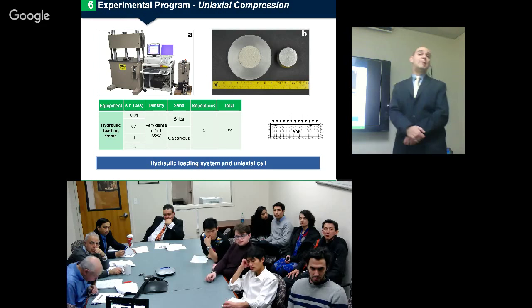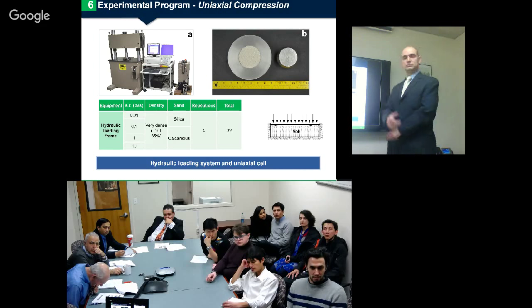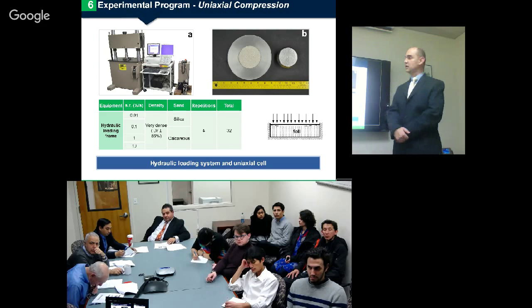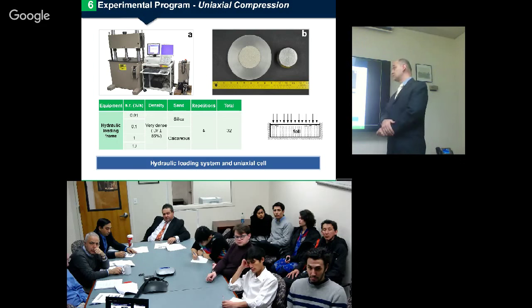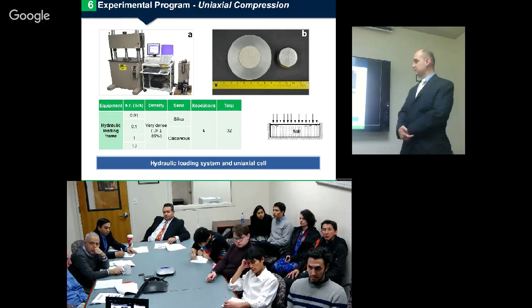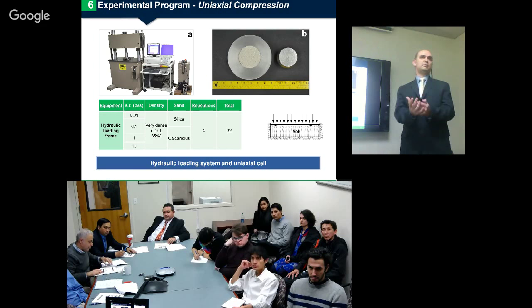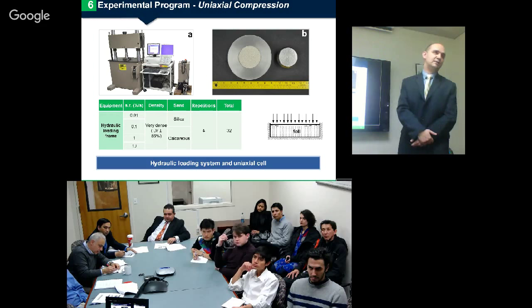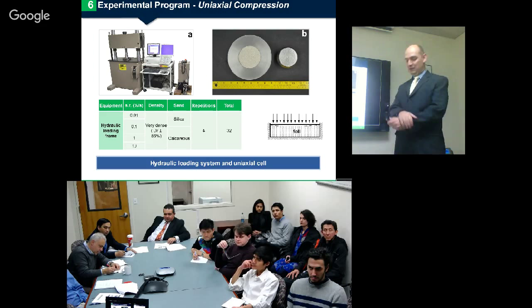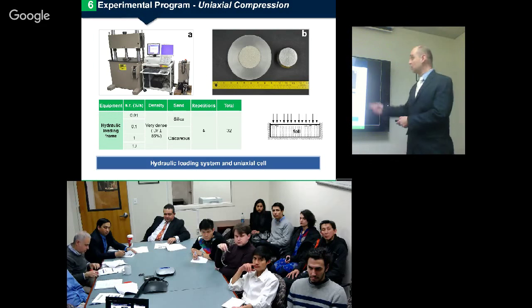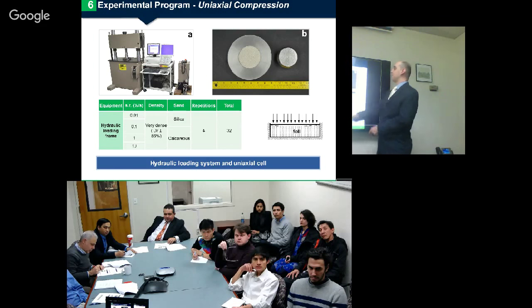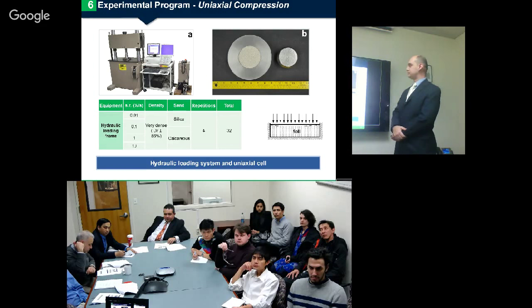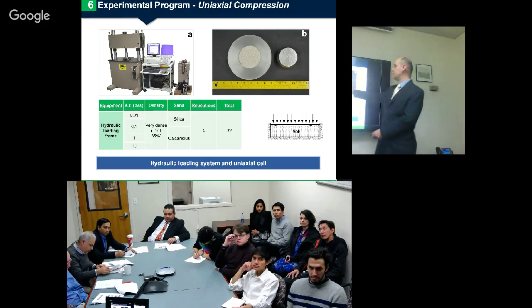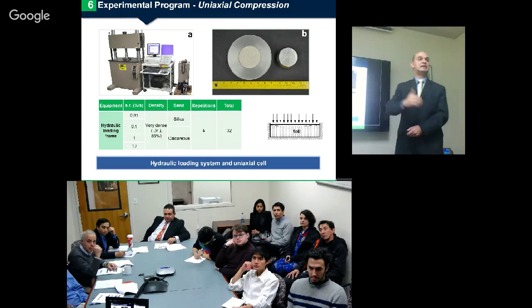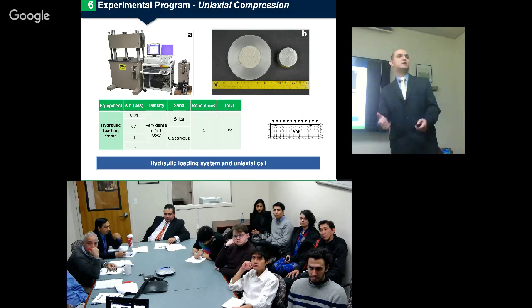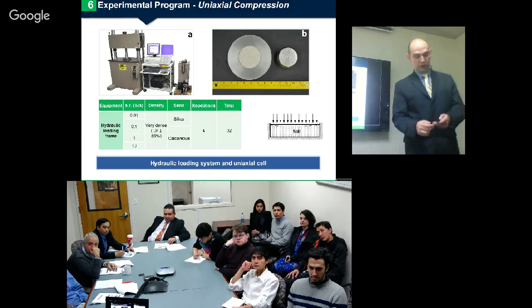Two different materials, made at very dense condition, obviously using the maximum and minimum density that comes from the ASTM standards. Repetitions, in order to find out the repeatability of the experiments, for a total of 32 good samples. Besides these 32, I think I ran about 100 tests in order to find out which ones are good tests. So we use this hydraulic frame, and I also created a 6 inch steel mold to house this material, plus the cap that is going to be on top of it, the transition between the ram and the material. And it's uniaxial because we are preventing lateral deformations, or we have these radial conditions.